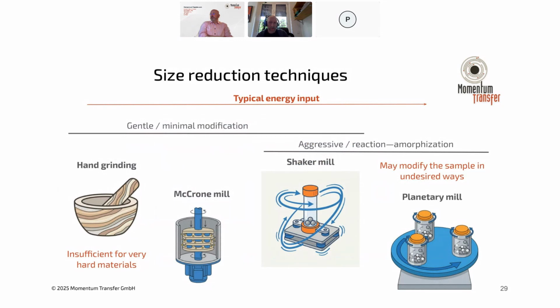For very hard minerals, hand grinding and sometimes even McCrone milling is not sufficient to really grind them down very well. Whereas if you overuse shaker or planetary mills, you can sometimes have a higher chance that you degrade the sample, either through significant crystallite size reduction, strain generation, or potentially amorphization. So you have to tailor the size reduction techniques to the particular mineral mixtures that you're working with to make sure you get optimal results. This is something that's often tested to find the best results, although there are generally recommended starting places for certain types of materials.